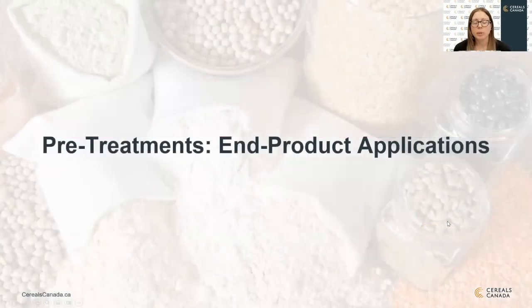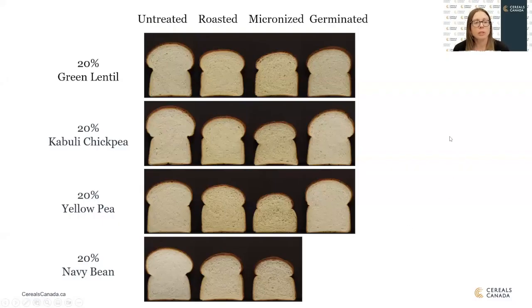So we also incorporated these into end products. Again, we looked at pan bread. You can see right off the bat that the roasted and micronized for all of the pulse types have a lower loaf volume, as well as a darker, more creamy colored crumb. And especially for the micronized, you see a large open round cell structure in the crumb, especially for the yellow pea sample. The germinated samples performed very well in this application.